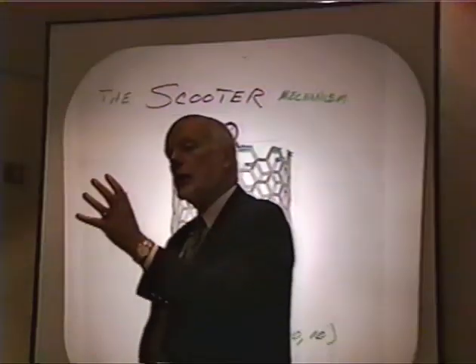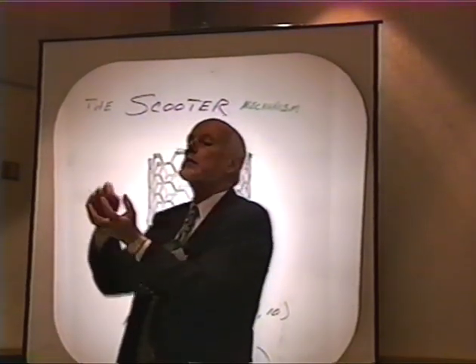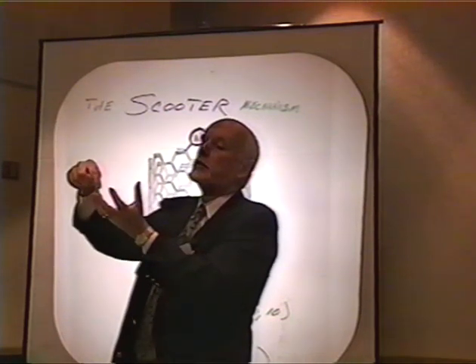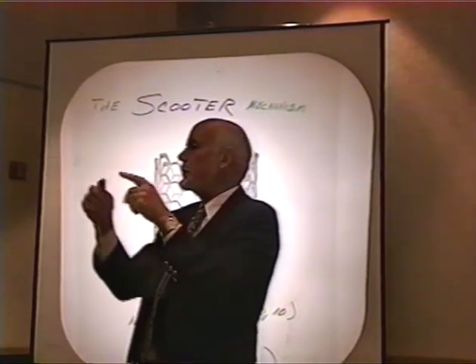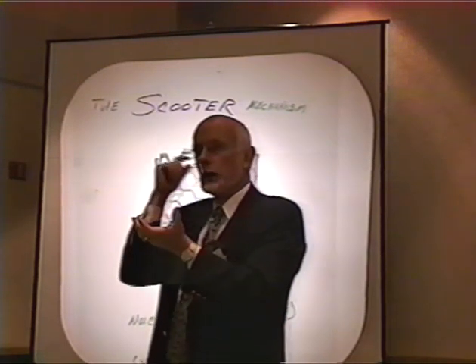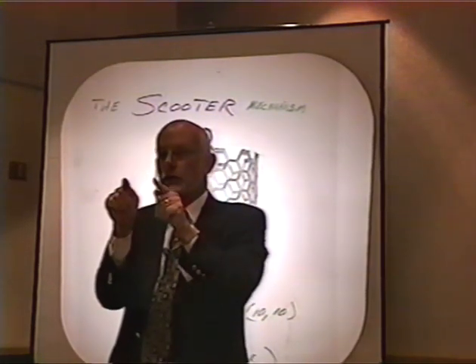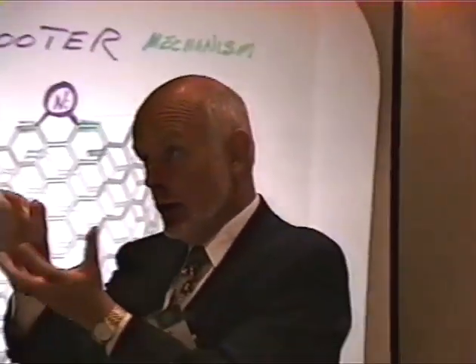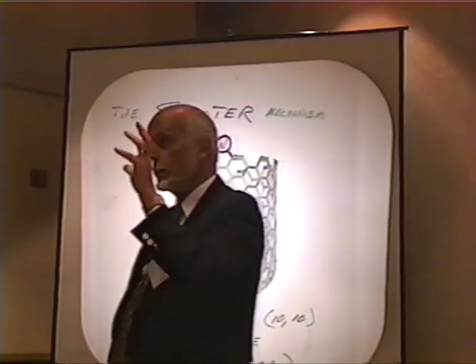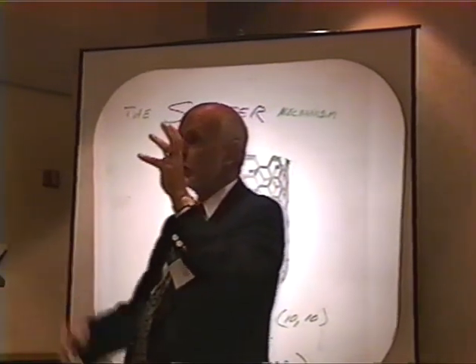One is it can rearrange so that there are pentagons in the structure. That gives it this positive curvature that allows it to reduce the peripheral circumference energy of this high energy edge. And the other is it can rearrange the positions of the pentagons so that at that exposed edge, you only have sides of polygons, not vertices. When you have the sides of the polygon, the carbon edge atoms always come in pairs, and you can form a fairly good, it turns out, triple bond with those edges. So that formally, if you could do it right all the way around the edge, there are no dangling bonds at all. There are just sort of mediocre triple bonds.